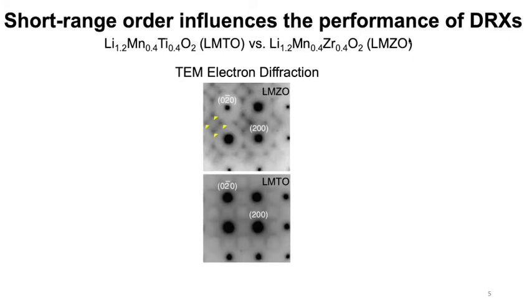Although there is no long-range ordering on the cation sublattices, there can be a significant amount of short-range ordering on the cation sublattices, which influences the frequency as well as connectivity of 0TM units. This will further control the capacity and rate capability of DRX materials. Here is a comparison between a DRX material, lithium manganese titanium oxide, and another DRX material, lithium manganese zirconium oxide. They are very similar in chemistry. However, as we can see later, they have very different electrochemical performance.